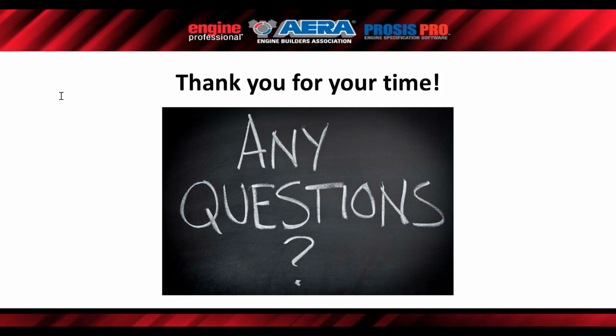Okay, we've got another question that came in for you, Chuck. Scott also has a question. Is hard chrome an okay sealing surface on a shaft? Hard chrome is a classification that means it's going to be measurable in 1.5 thousandths and greater to that diameter. Ideally, and I'm just quoting what came out of the RMA handbook, seal surfaces should not be run on chrome. The reality is there's an aftermarket sleeve company that chrome plates their sleeves, and I think they've been very successful with it. The big concern there is when you stretch it, you may fracture that chrome.